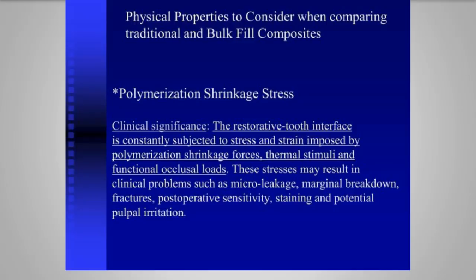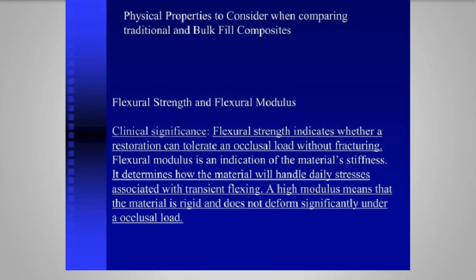We all know what this is. This is the key one right here, polymerization shrinkage stress, and this is the one we key in on, especially for bulk filling, because the restorative tooth interface, the interface of the adhesive seam to the tooth substrate, is constantly subjected to stress and strain imposed by polymerization shrinkage forces, thermal stimuli, and the functional occlusal load. So our bulk fills should really lower polymerization stress.